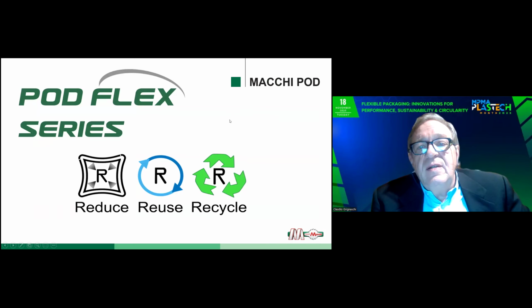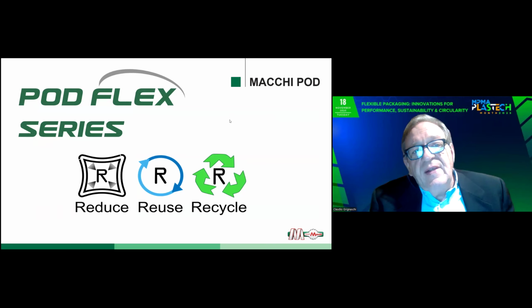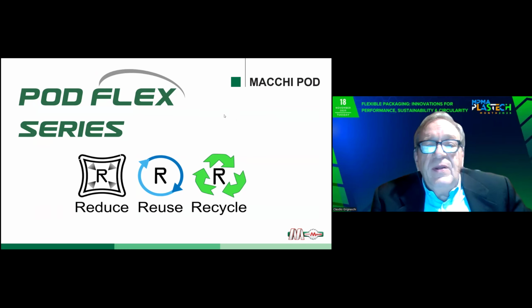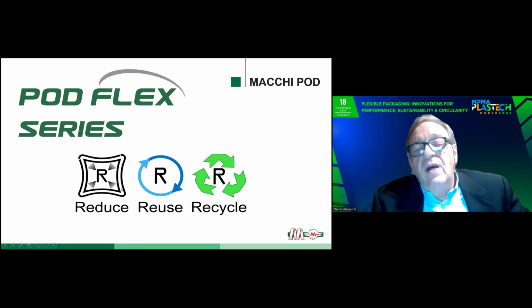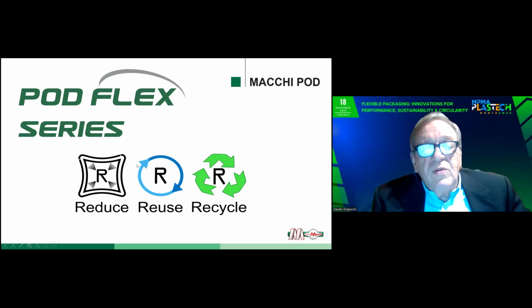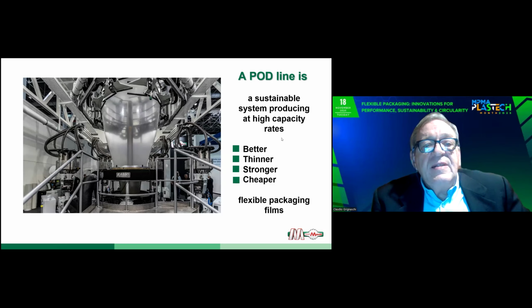But this was just another step. Everything started with the POD concept, which was targeted to allow converters to reduce the quantity of resin and therefore the energy needed, to allow for reuse of PCR, and to allow for easier recyclability of the material. A POD line, a polyolefin dedicated line, is a 5-layer line designed to run polyethylene structures and manufacture at high capacity better, thinner, stronger, and cheaper flexible packaging film.